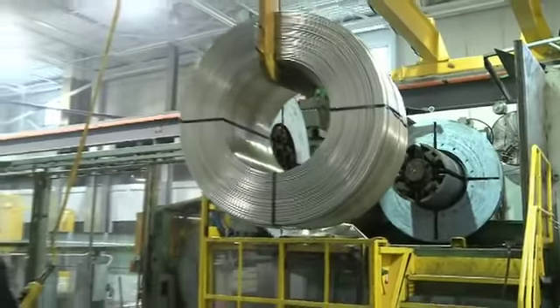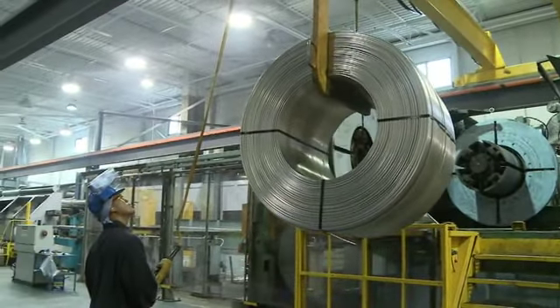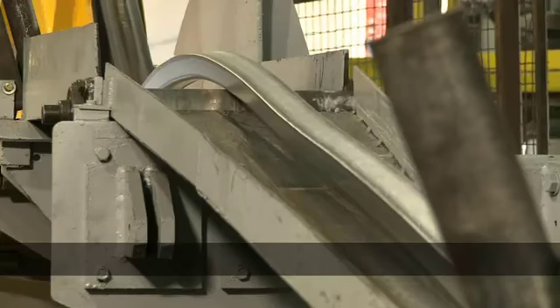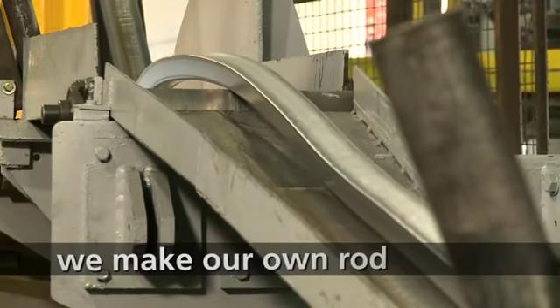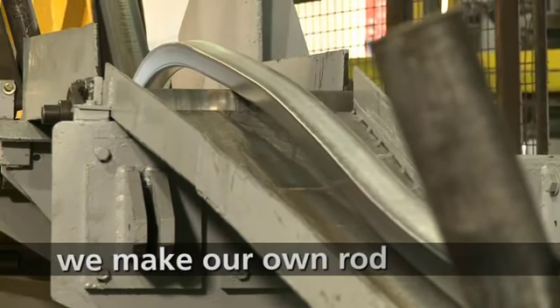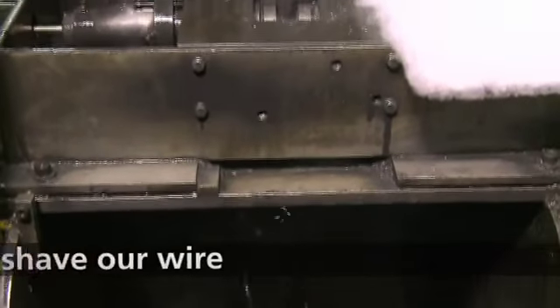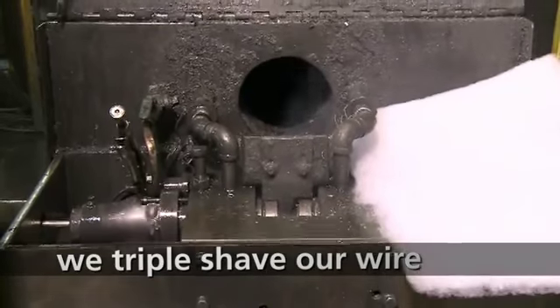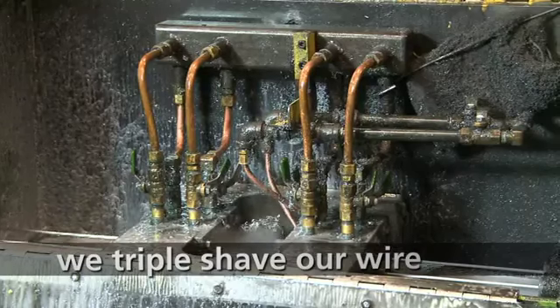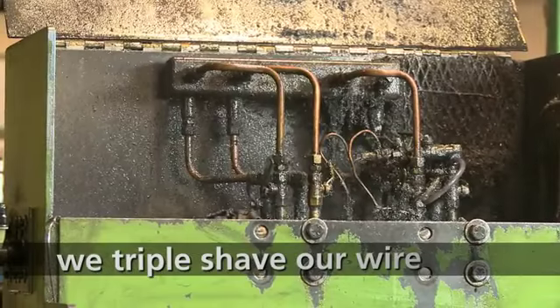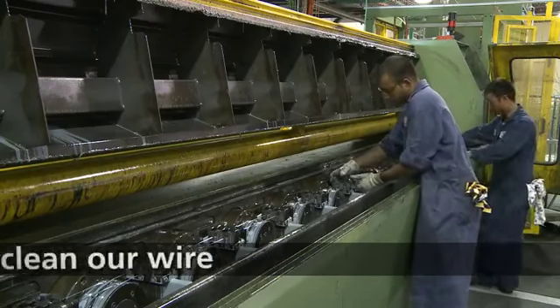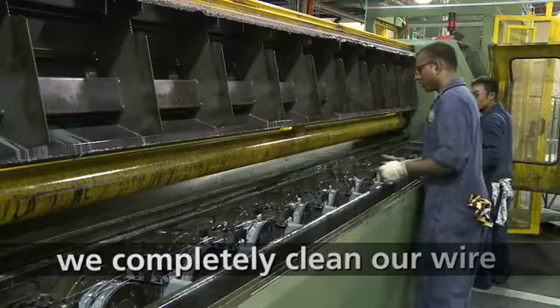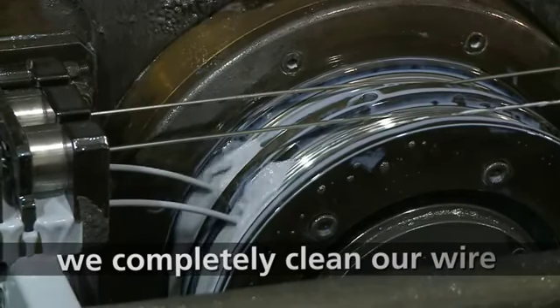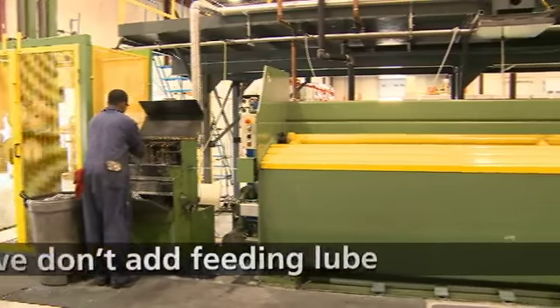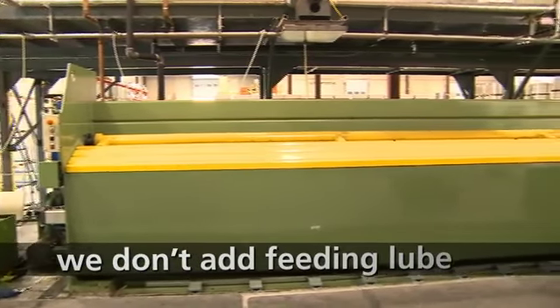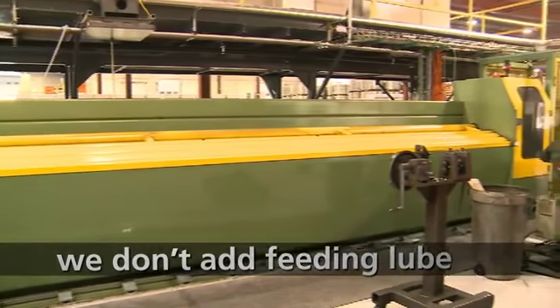Let's summarize what makes good aluminum welding wire and a good aluminum wire manufacturer. We make our own rod, which gives us security of supply and control over chemistry. We have extremely smooth wire as a result of 3 shaving stages. It improves feedability and leaves no place for dirt to hide. In the last stage of processing, we completely clean the wire, removing all contamination from previous processing steps. And we don't add spooling or feeding lube. Therefore, there's nothing left on the wire that could cause porosity in a weld.